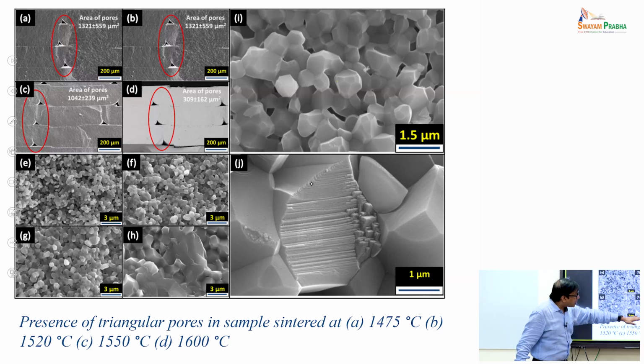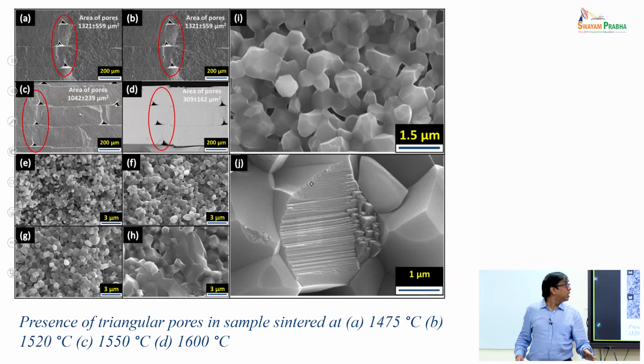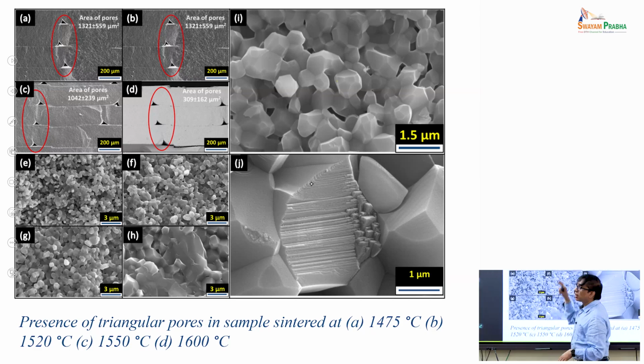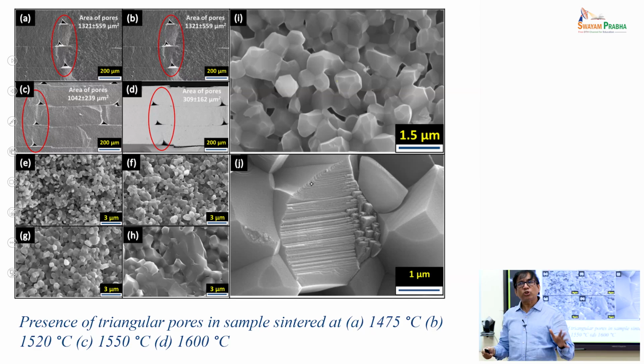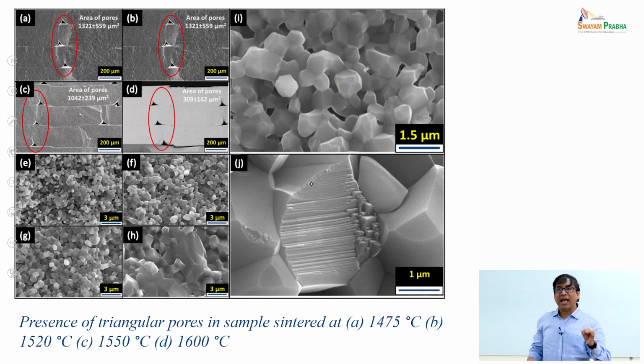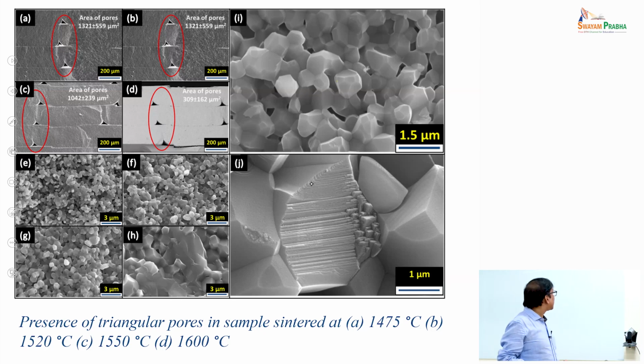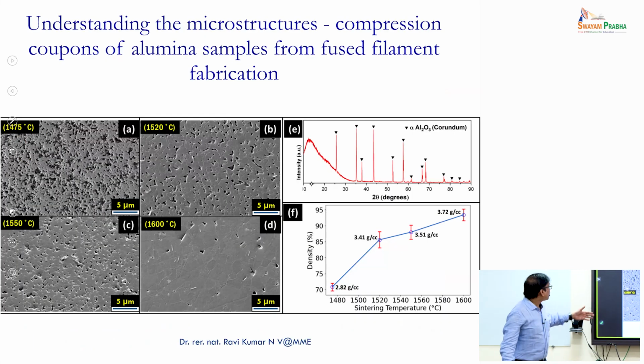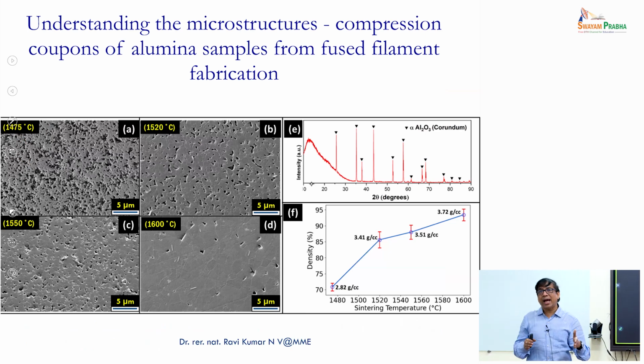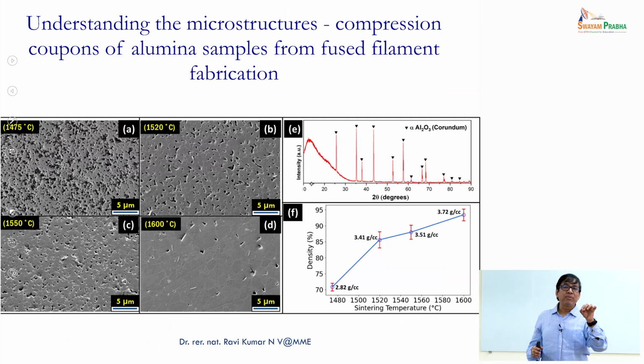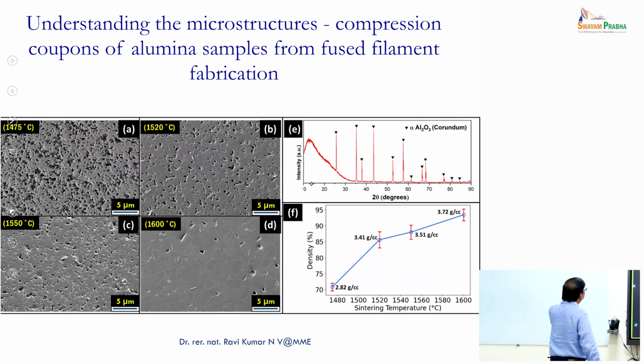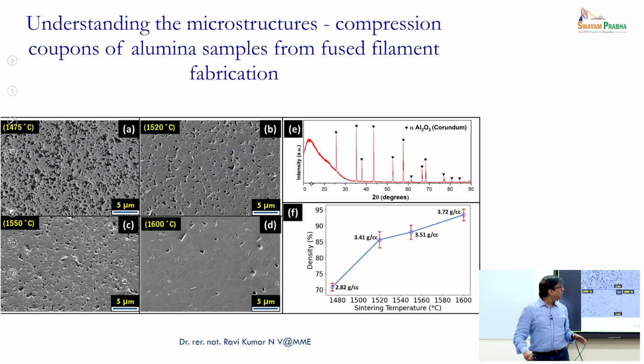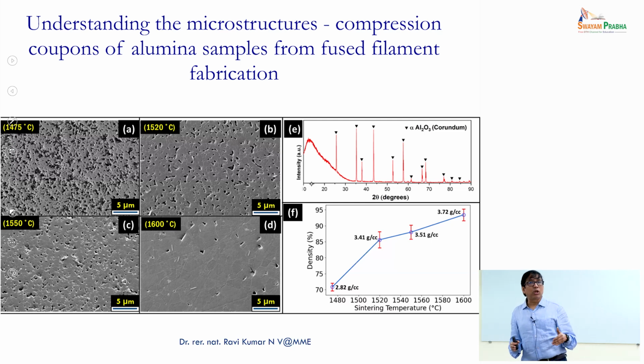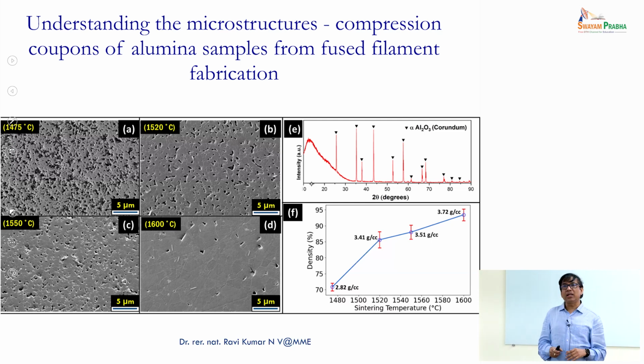Of course, they were sintered at various temperatures ranging from 1475 to 1600 degrees Celsius. But that is not the point. The point is what kind of defects do you still have? That will determine the compression strength values, and it's also showing you how sintering can change the microstructure in terms of the porosity distribution. From 1475 to around 1600 degrees Celsius sintering temperature, the pore fraction in the material could change, and that will definitely contribute to the tensile properties, relatively less in compression, but it does contribute.